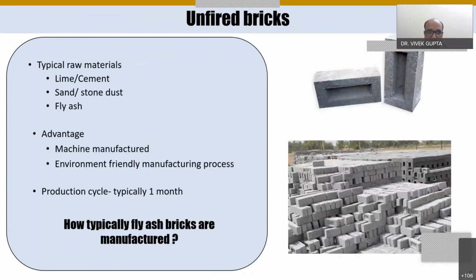So these are the unfired bricks, like typically in the market we see the fly ash bricks. The typical raw materials are either lime or cement as a stabilizer, and then sand or stone dust as fines, and fly ash we use generally as a filler material or a partial replacement of the binder, as it is well known that fly ash reacts with the lime and shows pozzolanic activity. So many researchers considered this as a supplementary binder in the bricks.